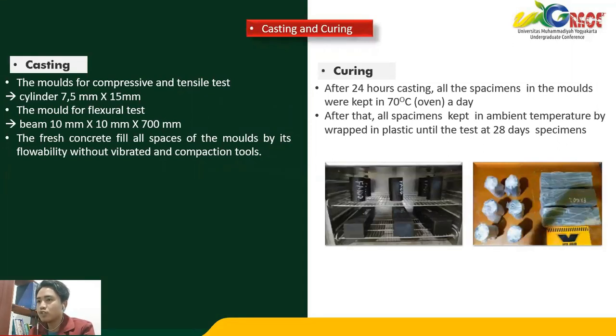So this is the casting and curing. For casting, we use two molds: a cylinder mold for compressive and tensile tests, and a beam mold for the flexural test. For all the specimens, the concrete filled all the space of the mold by its flowability, without compaction tools. And the curing: after 24 hours of casting, all the specimens in the mold were kept at 70 degrees Celsius for a day. After that, all the specimens were kept at ambient temperature, wrapped in plastic, until the test at 28 days.